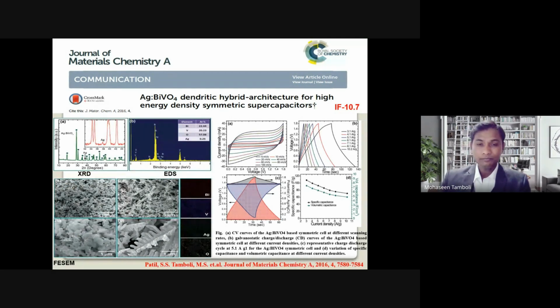After that, we studied the material for supercapacitor application. When we make the cell, these cells offer an extended voltage window of 1.6 V, which leads to an excellent energy density of around 2.63 milliwatt hour per centimeter cube, with high power density. This symmetric cell also exhibits a significant high capacity and good cycling stability, showing 82% capacity retention even after 4,000 cycles.